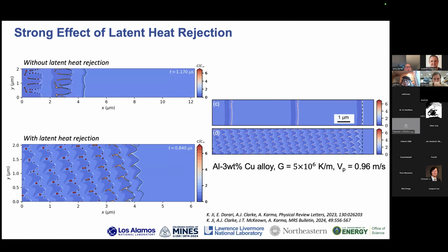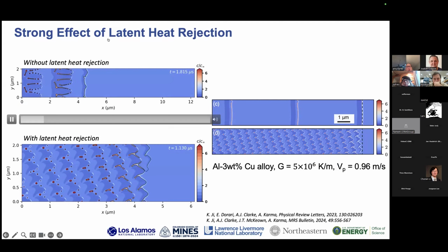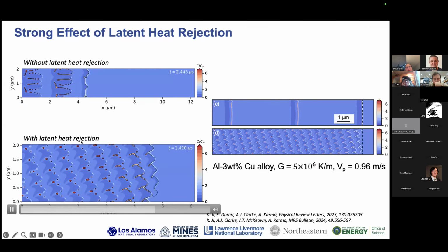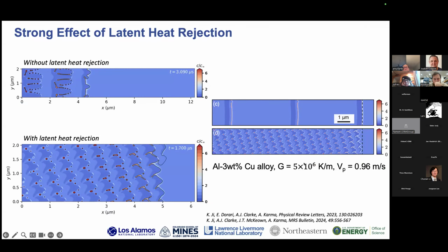And this just shows two example simulations, one without latent heat and one with latent heat. And basically the impact of that is on the length scale of the bands that we develop. So without latent heat, we form a much coarser microstructure as compared to including it. So it highlights that that's important in terms of actually getting quantitative predictions with our experimental data.